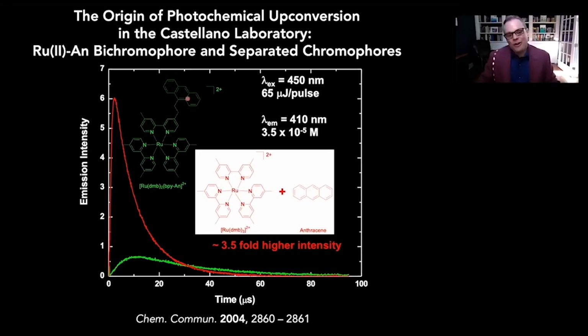But the problem was the singlet fluorescence here overlaps the metal to ligand charge transfer absorption band. So then we thought the intramolecular strategy for doing this would be terrible, because you're naturally going to quench the excited state you make by FRET. So we separated the chromophores.